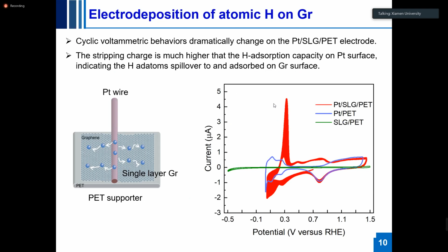If we composite the platinum wire on the PET-supported single-layer graphene, with this electrode we can see that the cyclic voltammetric behavior dramatically changed. We see a very big stripping current, which increases with the successive scans. The stripping charge is much higher than the hydrogen adsorption capacity on the platinum surface, indicating that the hydrogen atoms spill over from platinum to the graphene surface.